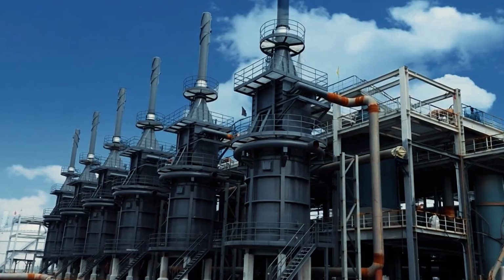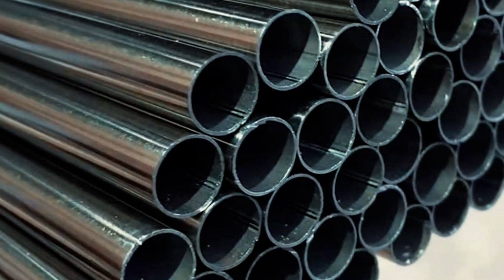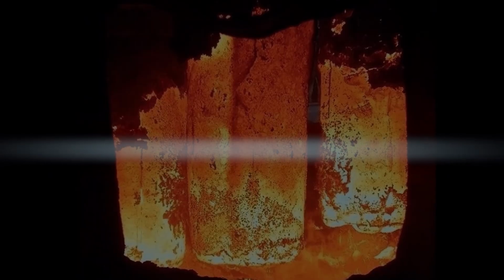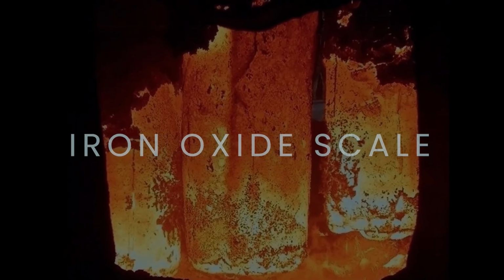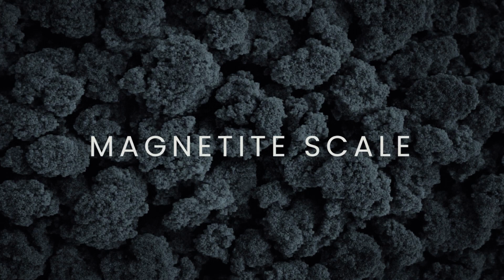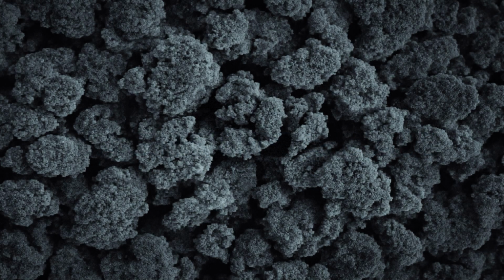You see, in most downstream fired heaters, radiant tubes are constructed from a low alloy steel. Let's say they typically run from a 2 to a 9% chrome, commonly referred to in the industry as P22, P9, P5, etc. Increasing the chromium content does improve oxidation resistance. However, all of these alloys will form iron oxide scale under just normal operating conditions. Even the 9% chrome alloys, which perform far better than 2.25 and 5, still develop magnetite scale. And that scale is ever present.